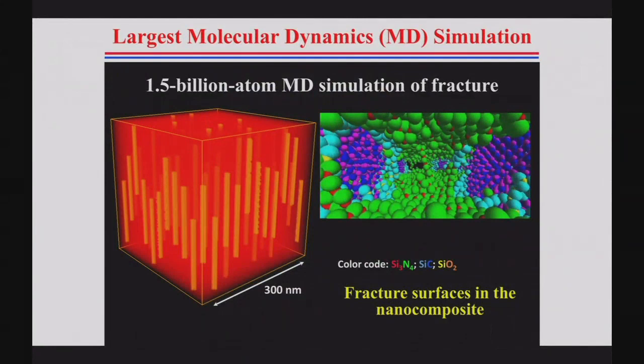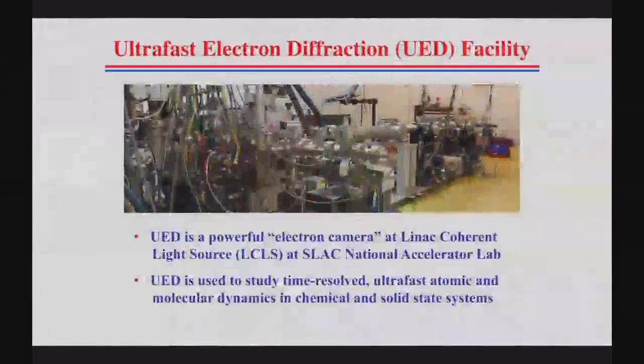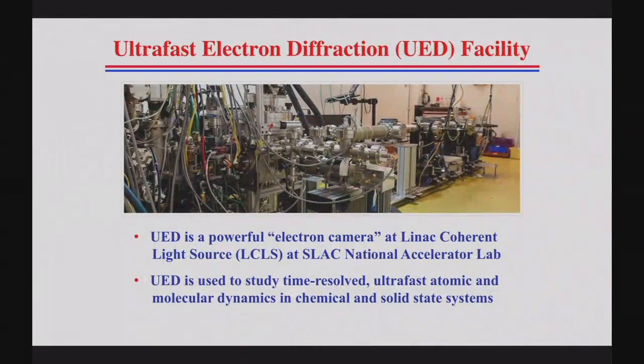Then to relate to experiment, there is this absolutely wonderful facility at Stanford, which is called the Ultrafast Electron Diffraction Facility. And we work with our collaborators at SLAC, Stanford, and they are doing experiments at this facility. It's an electron camera, so you put a material and you shine electrons on it. Electrons are diffracted from it, and when diffracted, these electrons give you information about where atoms are sitting in the material. And the resolution of this is less than 0.5 angstrom. That's how fine the spatial resolution is with this probe. Temporal resolution is less than 150 femtoseconds. It's an amazing facility.